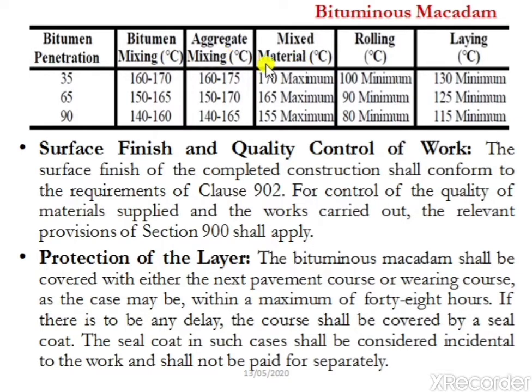The maximum temperature for this mixture is 170 degrees, and the rolling should be done at a temperature of 100 degrees, and it is the minimum temperature, and the laying of this mixed material should be done at 130 degrees minimum temperature. Similarly, for a bitumen,